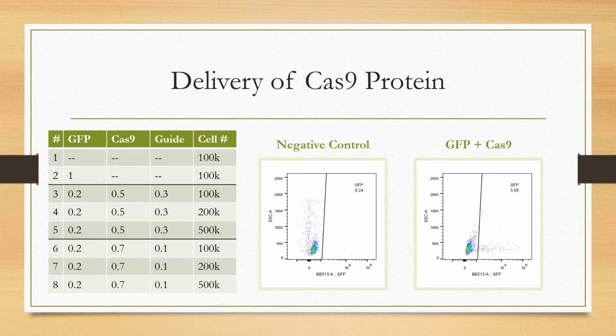We received similar results to the mRNA experiments, observing that in each sample, the cells were successfully transfected with the nanoparticles. Unfortunately, we were unable to complete enough repetitions of the experiments to definitively determine which combination of ratios had the best efficiency.